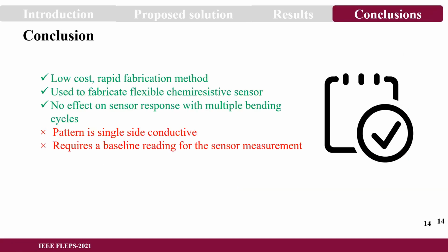So in conclusion, we have shown a low-cost rapid fabrication method for patterning leaf to make thin metal sensing electrodes. Here we have used this method to fabricate flexible chemiresistive sensors, where we used metal leaf as the contact electrode. We have seen that most of the sensors showed no effect on sensing response with multiple bending cycles. In this case, we have done up to 15 bending cycles up to 120 degrees.